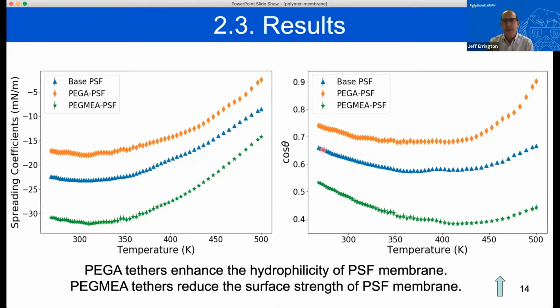You tend to see a decrease in the cosine of the contact angle at temperatures near room temperature as you increase the temperature, and then oftentimes see this minimum, and then as you go to higher temperatures, the cosine of the contact angle going up. Overall, though, if you take a look at these, the variation in the contact angle with temperature over this relatively wide range of temperature is not all that significant. And so in the end, we see the same rank order in terms of the wettability of the surface at room temperature as we did at 500 Kelvin.